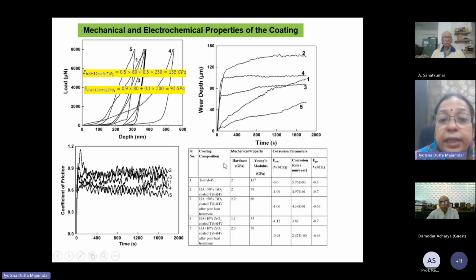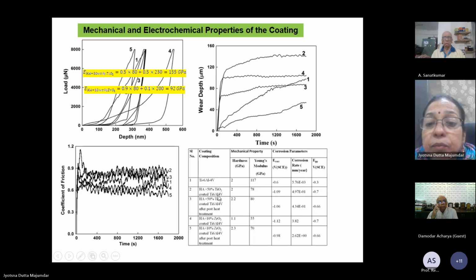Now if you quickly go through the mechanical properties and corrosion resistance of the coating, you will find that due to addition of both TiO2 and ZrO2, there was significant improvement in corrosion resistance, and the Young's modulus of the coating was reduced as compared to Ti6Al4V. But the corrosion resistance was still not as high as Ti6Al4V because of the higher dissolution rate of hydroxyapatite. However, when compared with the pure as received HA coating, we found that the dissolution rate decreased because of the presence of TiO2 particles.